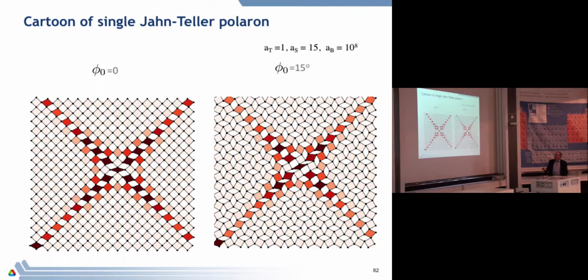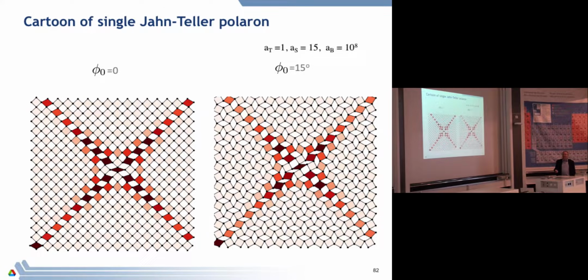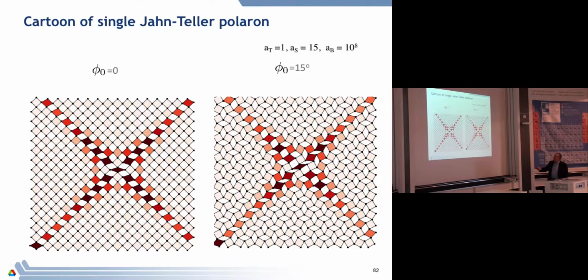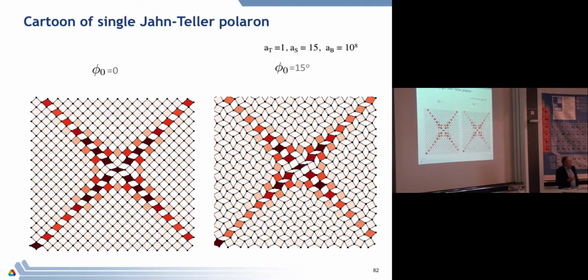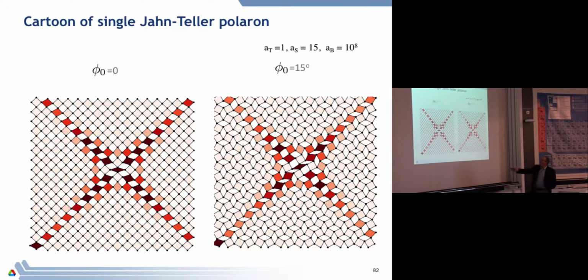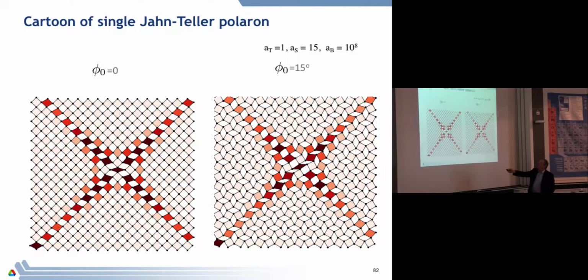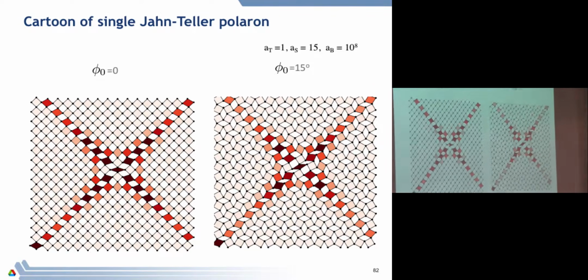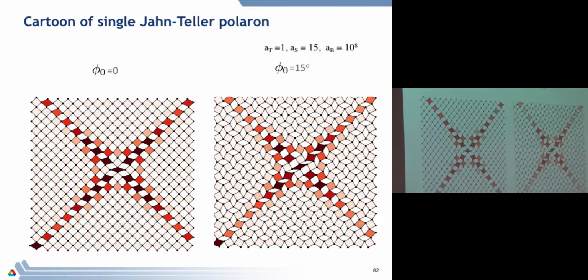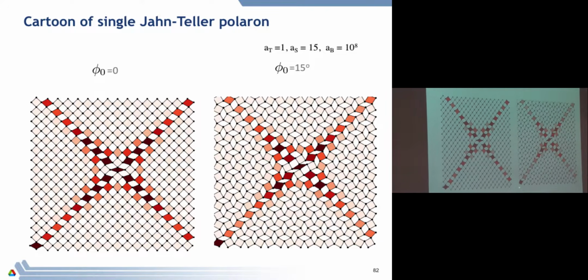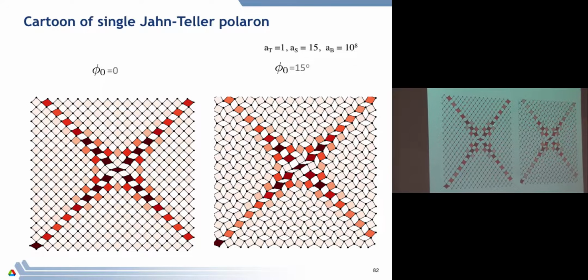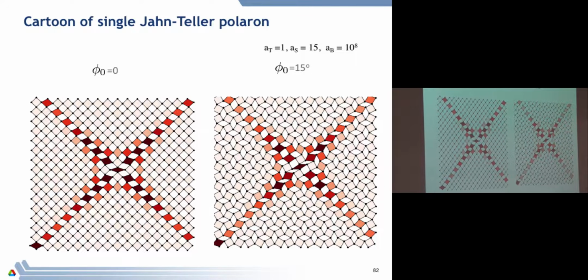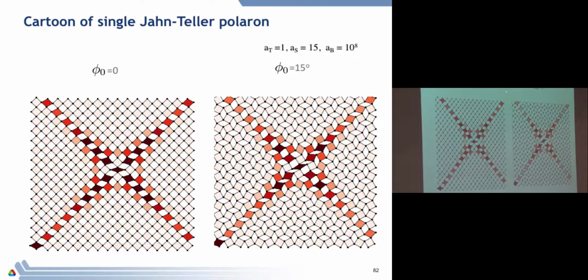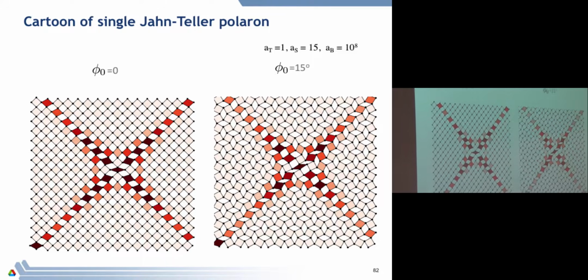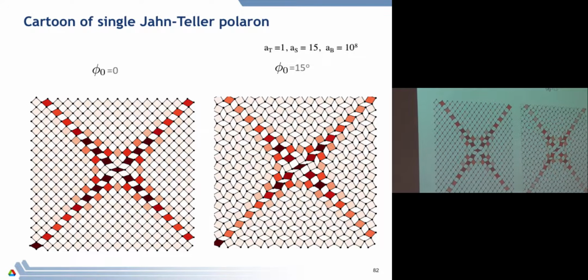But for example, what it really means is, if you look at, here's a cartoon of a Jahn-Teller polaron, I just put a single one in the middle of the lattice. By putting a single one in here, it pushes out and tries to deform all of the others, and you see that the compromise it produces eventually is this star-shaped pattern along here, where these are the strain fields generated from here, and they extend out to infinity.